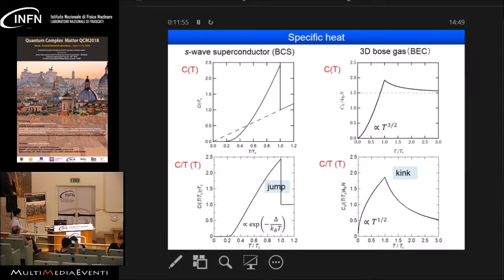And here is a very simple comparison between the s-wave BCS superconductors and the simplest BEC, which is the 3D Bose gas. Okay, so let's look at C over T as a function of temperature. And in the case of BCS superconductors, as you know, we should have a jump at Tc, right? Because we have a second order phase transition. And in the superconducting state, it depends on the structure of the superconducting gap, but if you have a fully gapped state with no nodes, then you should expect exponential decay at low temperatures.